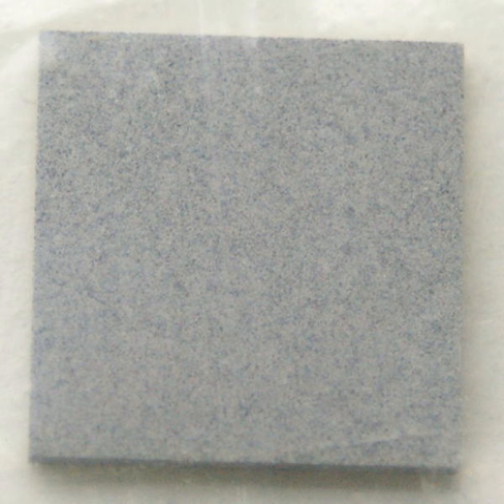Electronic-grade silicon nitride films are formed using chemical vapor deposition, CVD, or one of its variants, such as plasma-enhanced chemical vapor deposition, PECVD. 3SiH4 (g) + 4NH3 (g) → Si3N4 (s) + 12H2 (g) at 750 to 850 degrees Celsius. 3SiCl4 (g) + 4NH3 (g) → Si3N4 (s) + 12HCl (g). 3SiCl2H2 (g) + 4NH3 (g) → Si3N4 (s) + 6HCl (g) + 6H2 (g), for deposition of silicon nitride layers on semiconductor, usually silicon, substrates.